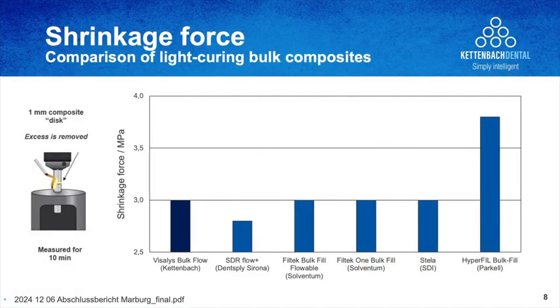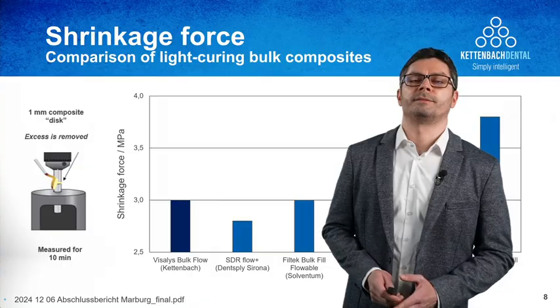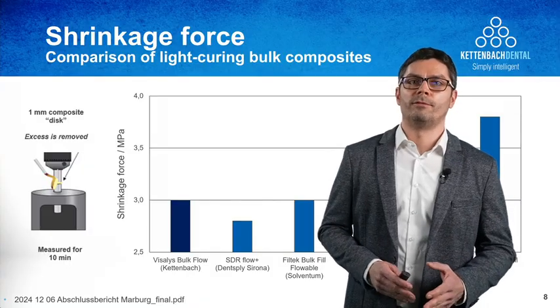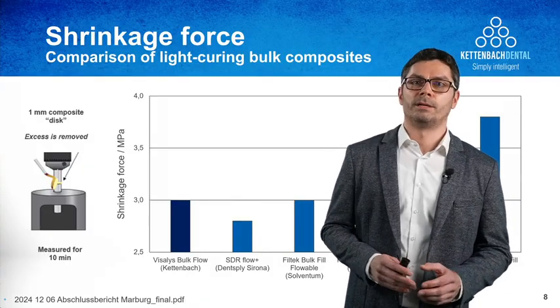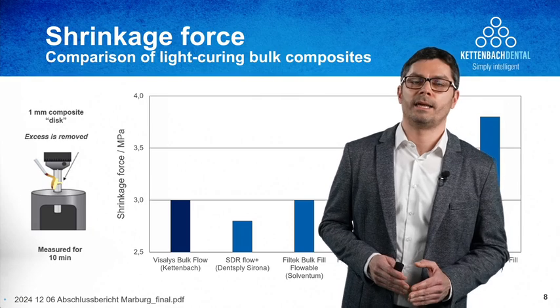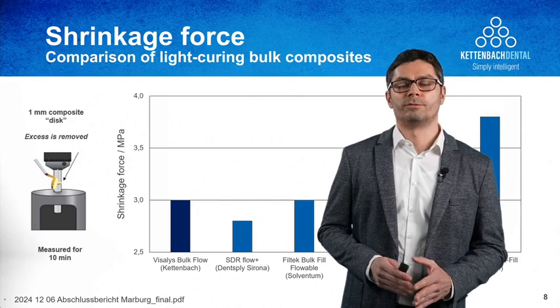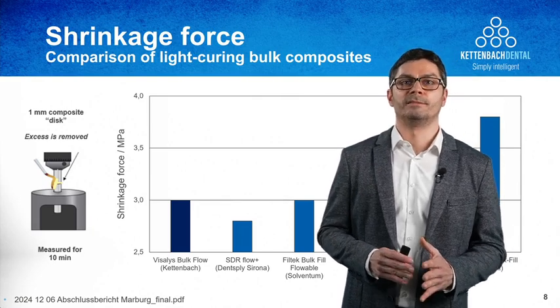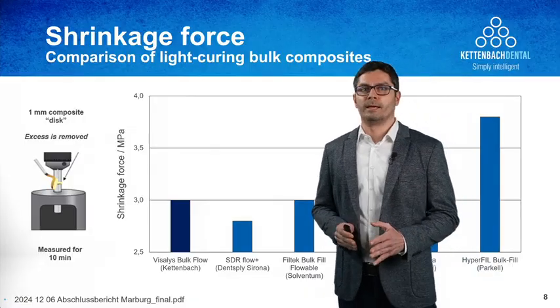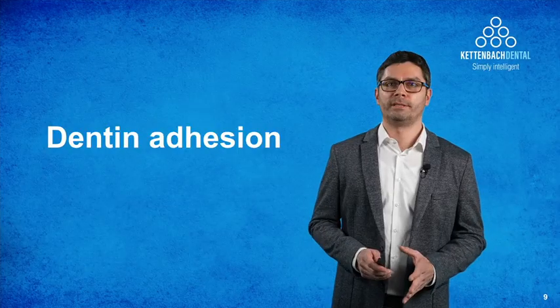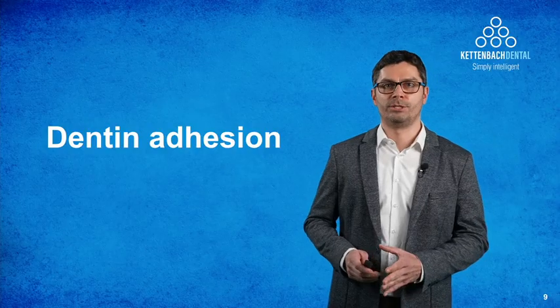After a very high number of formulations, we found a composition that is very low in shrinkage, as you can see here on the left. This is due to a very high filler content, well distributed filler sizes, and the monomer matrix. It's very important to have a monomer matrix that is not high in shrinkage. And that's what we could see here. If you have a look at other products, they are much higher in shrinkage force, or can be much higher in shrinkage force. So a low shrinkage force was the first thing that we could achieve.